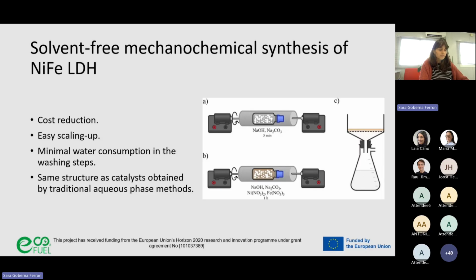In this approach, the catalyst is obtained simply by mechanical grinding of the solid precursors for 1 hour at room temperature. We don't use any solvents or any external heating. An important advantage of this route is the significant reduction of cost and environmental impact, since we eliminate solvent, minimize energy inputs, and reduce water consumption during the final washing steps. And actually, we obtain the same structure as the catalyst obtained by traditional aqueous phase methods.